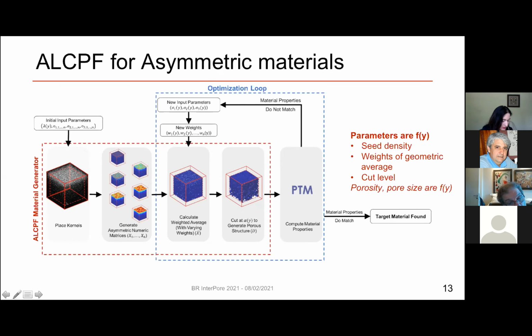Similarly, other parameters such as the weights that we will give to each one of these domains are different. And the cut level is also a function of Y. So the result is that the material properties such as pore size and porosity become a function of Y, and this is how you control the gradient of pore size and pore distribution along one dimension.